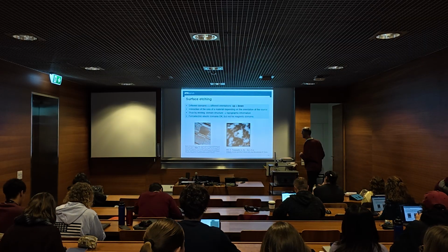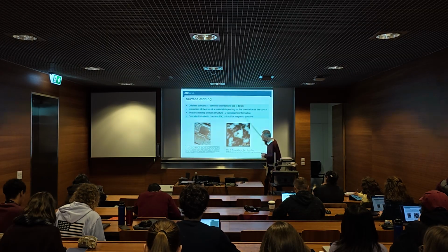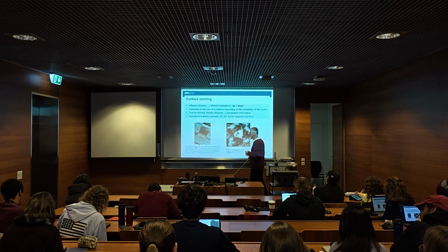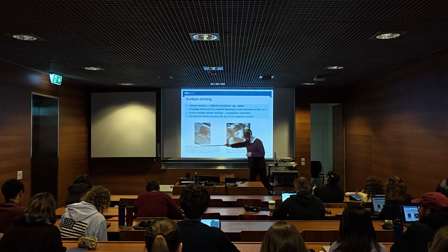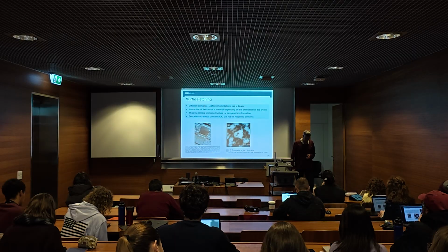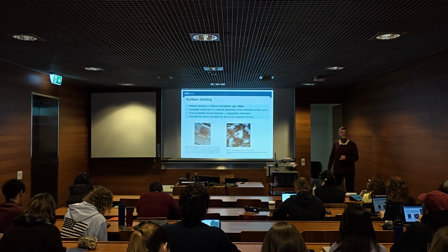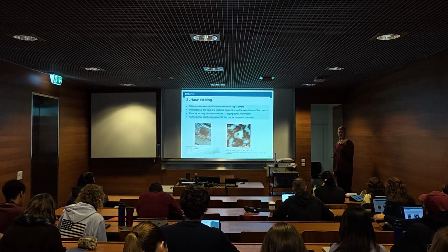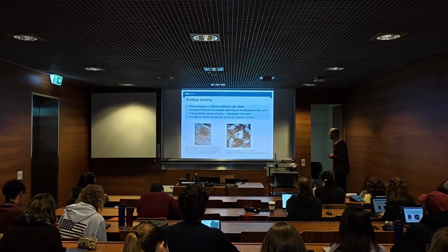Chemical processes can make use of that, and if you put an etching agent on the surface, for example of a ferroelectric, in this case barium titanate, here yttrium manganite, then the etching is different for the two domain states, simply because the etching agent sees different surfaces with a different distribution of ions.